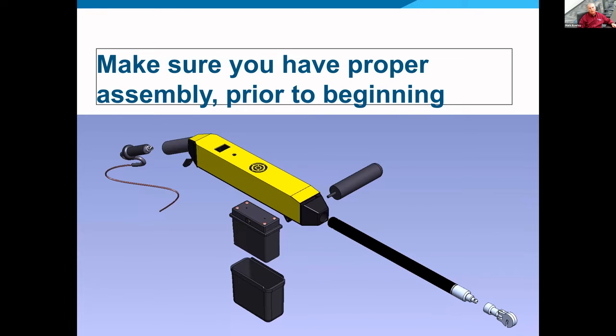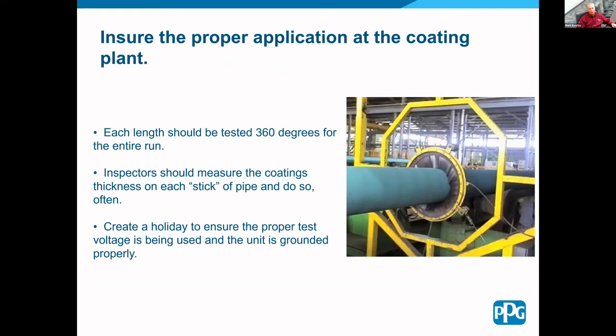So one of the things we want to do is when the coating's applied, in the plant, just prior to coating or just post coating, we want to make sure that everything is checked 360 degrees in the case of pipeline, on the exterior. Tanks, again, every square inch gets inspected with a holiday detector to make sure that there are no voids, holidays, pinholes. The inspector should measure the coating thickness. This is extremely important, and we'll go through this a lot more during the slide presentation. But we want to make darn sure that when the applicator tells us we have 30 mils or 10 mils on the pipe, that's exactly what we have on the substrate. That we have exactly what they've applied, not what they've told us that they've applied.